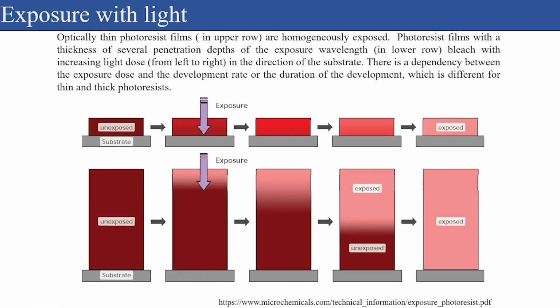So the next step is in the exposure of the light, we need to have an optimum exposure dose and the exposure time. As we can see from this figure, this is an example of a thin resist film, and this is an example of a thick resist film. Now when a thin resist film is exposed to the light, with time we can see that the structure is being exposed and a uniform exposure happens. That is, it is homogeneously exposed.